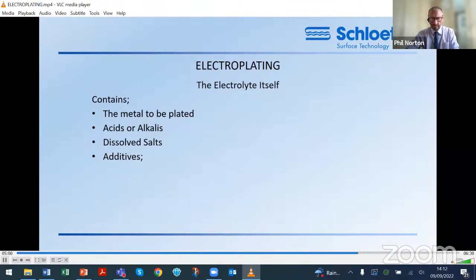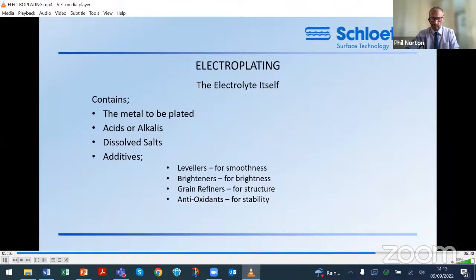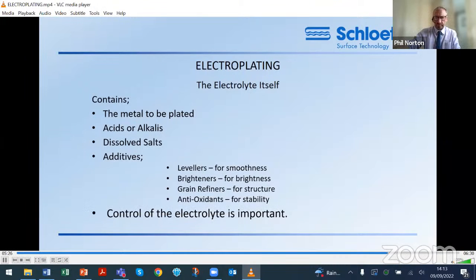Proprietary additives which modify the plating reaction, for example levelers, which make the deposited metal smooth, brighteners, which make the deposited metal bright, grain refiners, which modify the structure of the metal being deposited, and antioxidants, which help stabilize the mixture. All these can result in a complicated mixture, and it's important to maintain the electrolyte properly so as to obtain consistently good plating results. This is where specialist suppliers can help.